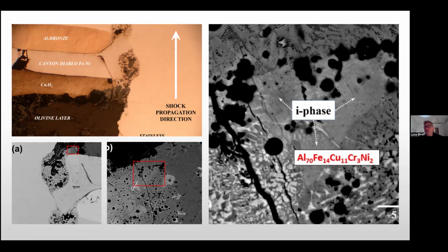But since I was very curious to see the degree of structural perfection of this icosahedral phase, I decided to extract a small grain from this tiny polished surface and collected single crystal X-ray diffraction data, because you have to know that quasi-crystals, even if they are very small, are very highly diffracting. And I'm going to show you what we got in terms of all the diffraction data collected down the five-fold symmetry axis.